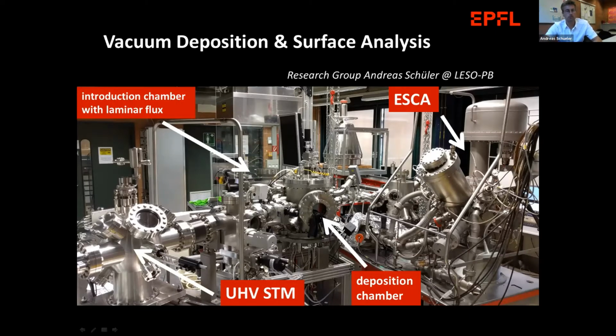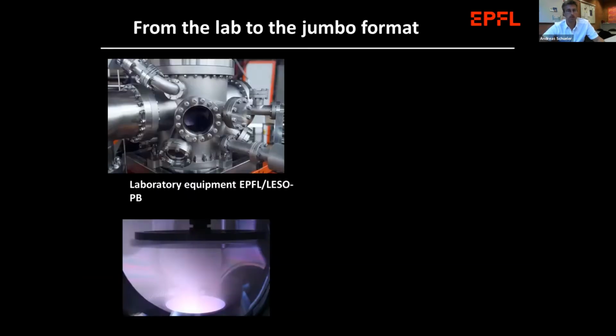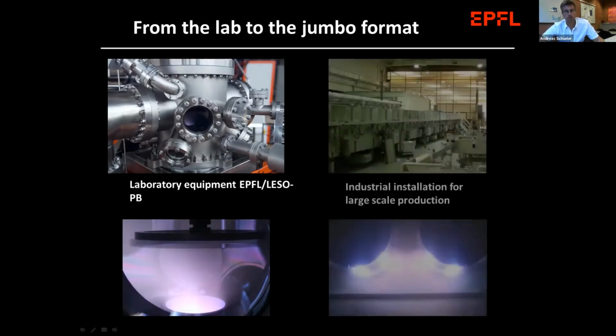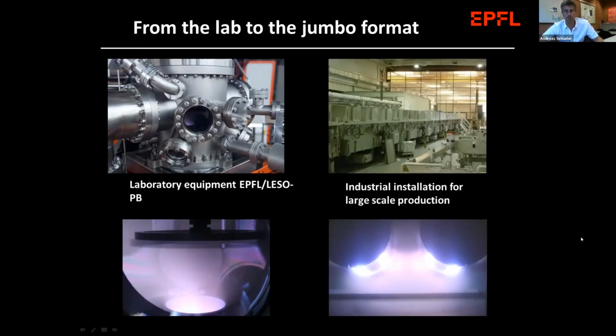So a great advantage of the system is that we can make a sample and analyze the surface of the sample without taking it out to air. So we have a very good image of the as prepared surfaces. Here a close-up of the film deposition. It's a plasma deposition. So we do have in the center of the chamber magnetrons. Those are magnetic electrodes. We would ignite a glow discharge here. This is a cold plasma, and then we would have film growth here on the opposite side, where we would put the substrate.